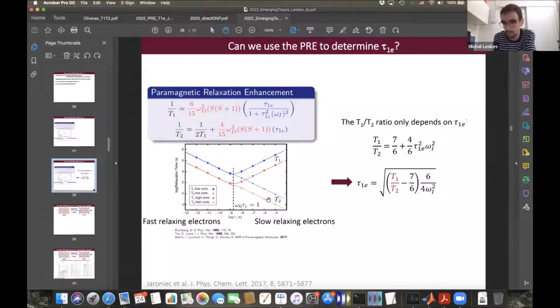The curves were relaxing with a stretch exponential factor beta of about 0.5, and this is something that is known from the old days, from Bloembergen and so on, that when spin diffusion is efficient, you have a common spin temperature throughout the system. So all spins tend to relax together, and in this case you get a mono-exponential relaxation behavior. But when spin diffusion does not play a role, then you get this distribution of relaxation times that turn out to look like a stretched exponential.